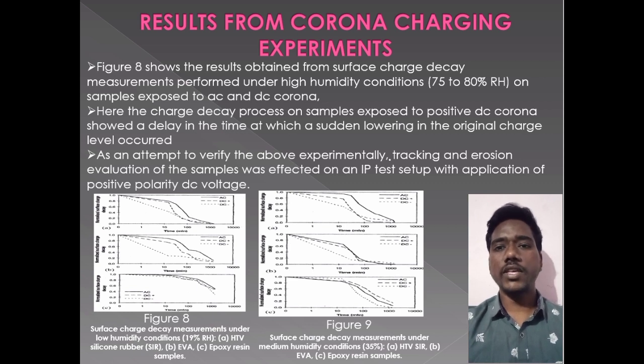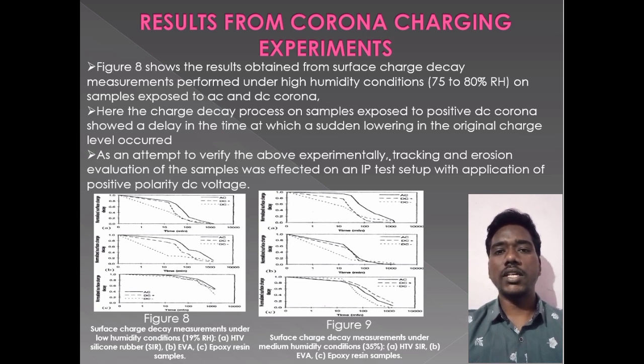The results from surface charge decay measurements under low humidity conditions are summarized in the figure for relative humidity of 19% and 35% respectively. From these results, several features can be highlighted. Significantly higher magnitude of surface charge was registered after treatment of samples with DC corona as compared to the AC case. Slightly higher initial magnitude of surface charge density was recorded in samples exposed to positive polarity DC corona at 19% RH with respect to those measured at 35% RH.